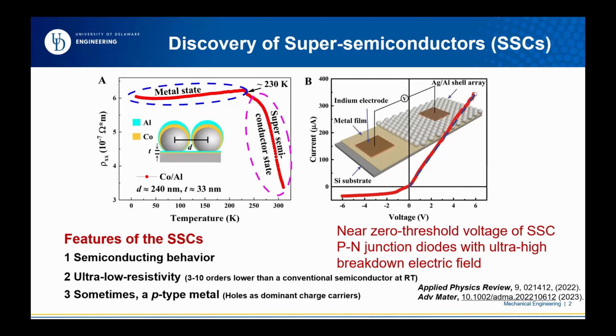So here we got 0.01 volt. That indicates that if you just use a very small voltage, you can turn the device on and off. At the same time, if you look at the breakdown voltage, it goes up to 10 to the 6 volts per centimeter.